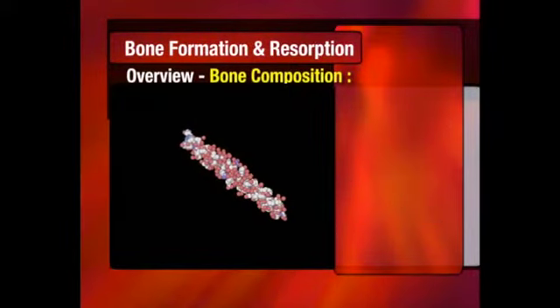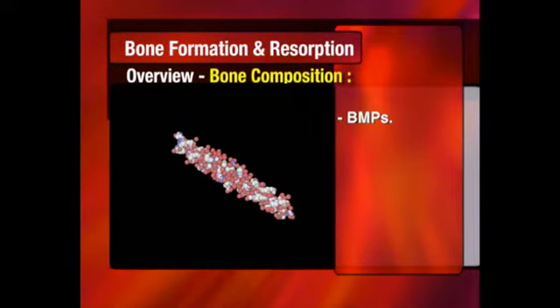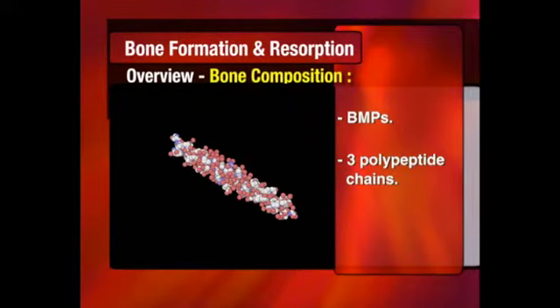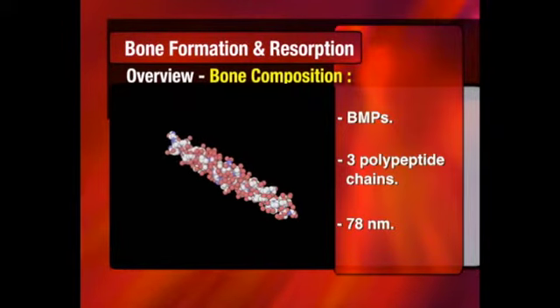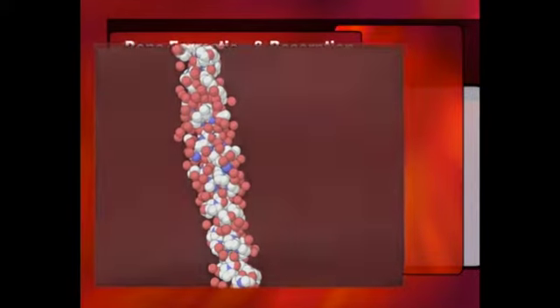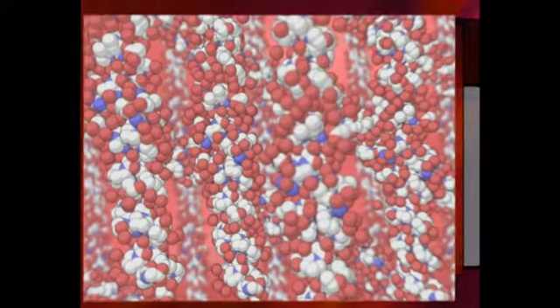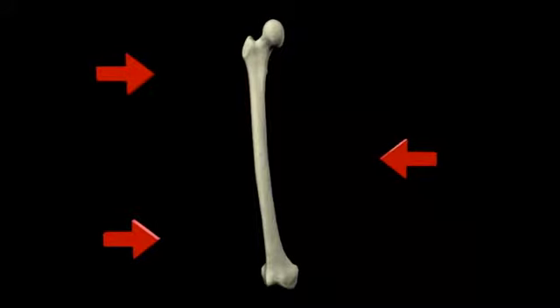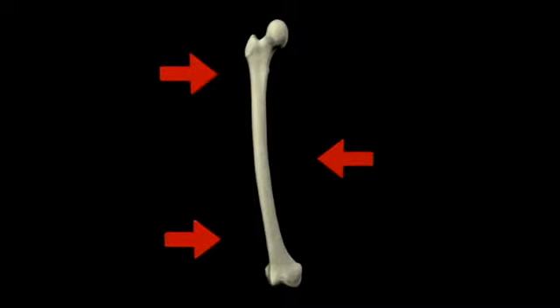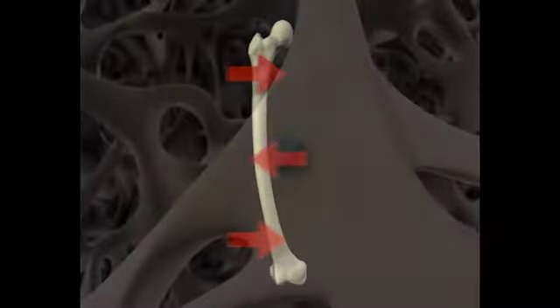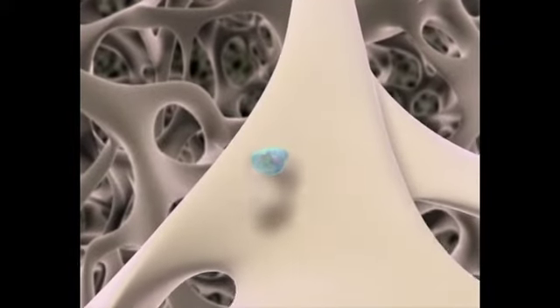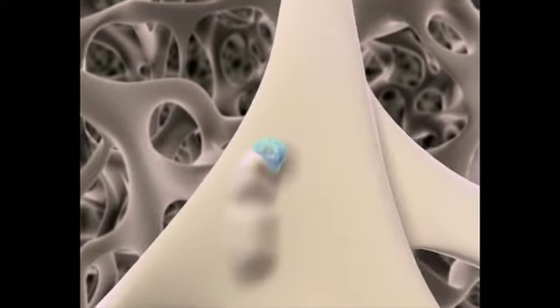Importantly, the matrix also contains bone morphogenetic proteins. A type 1 collagen molecule is comprised of 3 polypeptide chains. The molecule is about 1.5 nanometers in diameter. The organic matrix is principally a 3-dimensional cross-linked array of the type 1 collagen molecules. The collagen gives bone flexibility and tensile strength. It also provides locations for the deposition of the mineral phase of bone, which gives the bone rigidity and compressive strength.